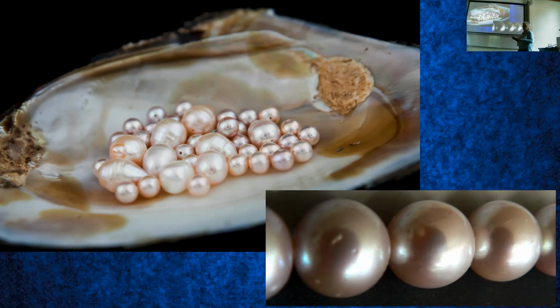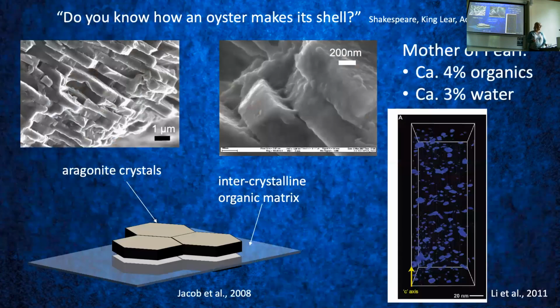And we found that while the pearl is aragonite, these white spots consist of vaterite, which is a polymorph of aragonite with a different crystal structure. At that point in time, the crystal structure was not known. And that just influences the luster of the pearl, so they couldn't sell it. So one thing led to the next, and in the end, I actually had a fully fledged research project, which then got me a future fellowship, and here I am, still working on these things.